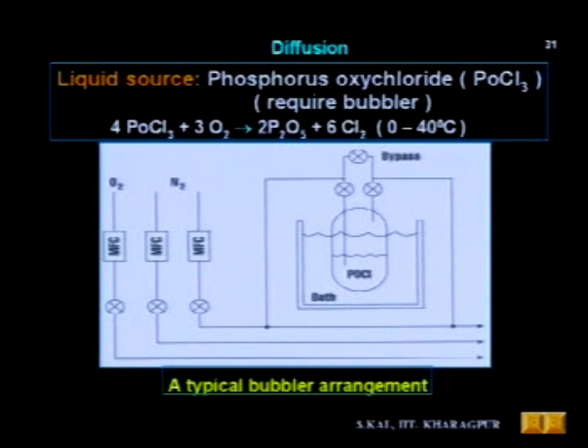If you increase the bath temperature, then the vapor pressure also will increase. But for standardization, we maintain the bath at a constant temperature, so that when we repeat the process, we will get repeatable result, because the vapor pressure of the POCl3, we keep it constant at certain value, and that vapor pressure is dependent on temperature. It is very easy to keep the temperature 0 degree, because easily you can use some ice and it will attain the ice temperature. Okay. So that's why in our laboratory we use ice bath for POCl3 diffusion.